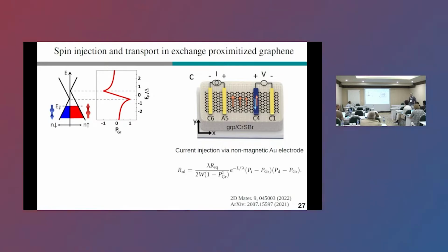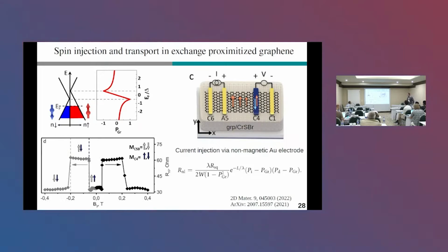And now let's see if graphene really is polarized. This is what they measure. At 0 field, they measure a low resistance state, which means the graphene and the detector, the cobalt, are parallel polarized. At some field, the cobalt switches and we go to a higher resistance state. And at an even higher field, the substrate switches, which brings us back to a low resistance state. So when the substrate switches, the proximity exchange switches. And this means also the polarization in graphene switches. And this experiment very nicely demonstrates that we can use proximatized graphene for spin injection without the need of conventional ferromagnetic electrodes.